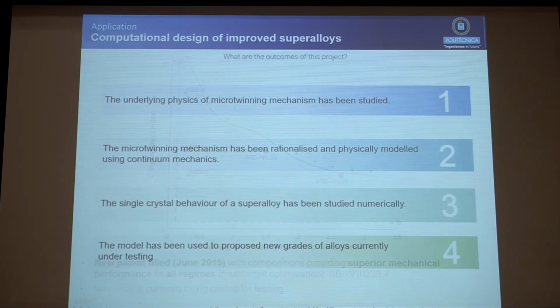And basically the conclusions of the work are: we have studied the underlying physics of the mechanism from a multiscale experimental point of view. The microtwinning mechanism has been rationalized and physically modeled in the continuum model. And we have studied the single crystal creep behavior of the alloy I have shown before, and it has been studied numerically, and we have also used this model to propose new grades of alloys that are currently under testing.